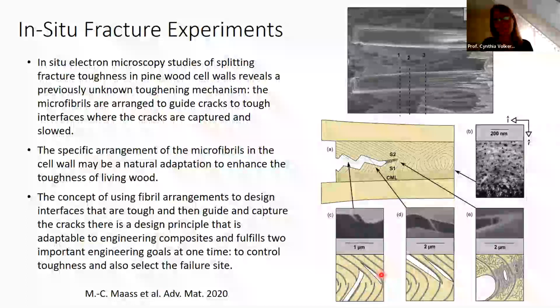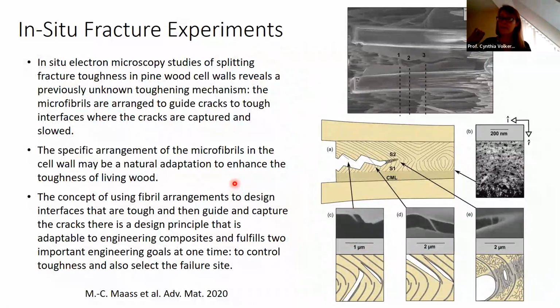And the thing we found really fascinating about this is we believe that, learning from the structure of wood, this study showed a new concept for how one can make fibrous materials tougher. The basic idea in wood is that the fibrils are arranged so the cracks are steered to a particular interface. At this interface, the fibril direction changes, and the cracks get hung up. They have to stop, they have to tear and rupture the fibrils, which requires a lot more energy before they can continue on. So basically the material is designed so that it steers cracks to a very tough interface, and the cracks get trapped there. In order for them to move further, it requires a lot of energy. So it becomes a tough material.